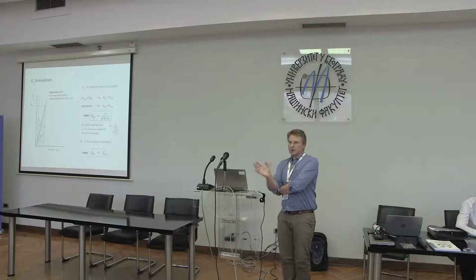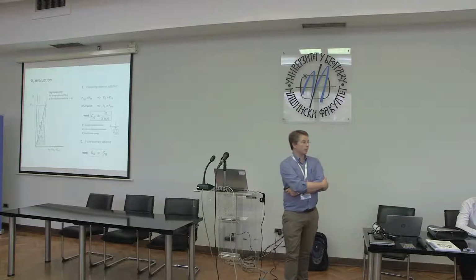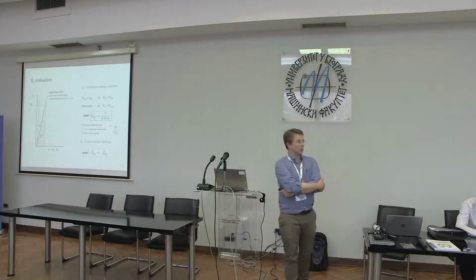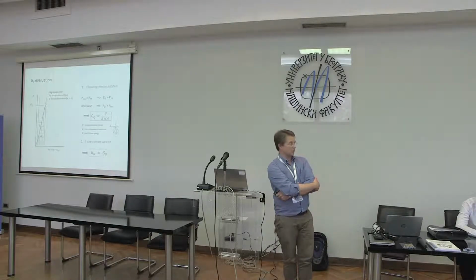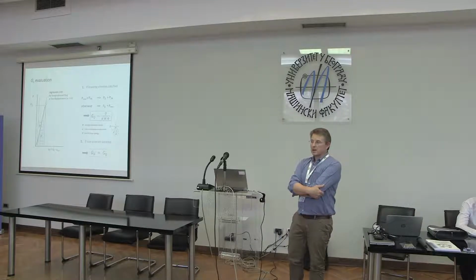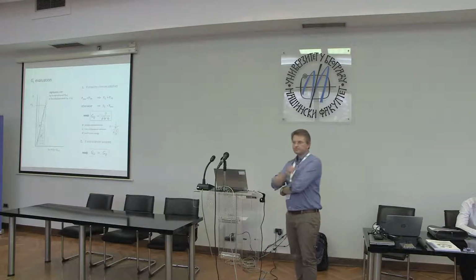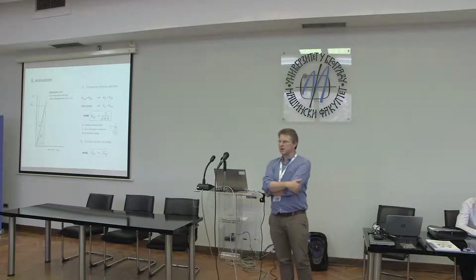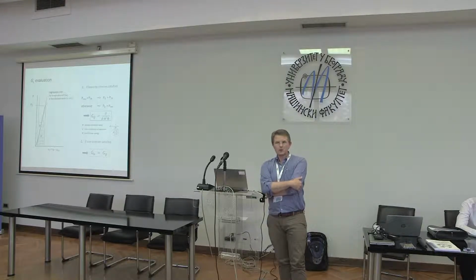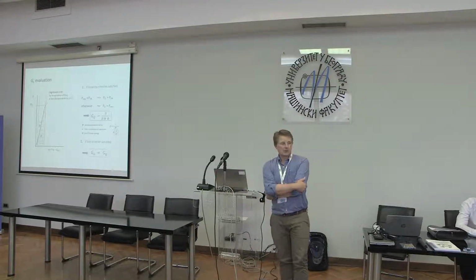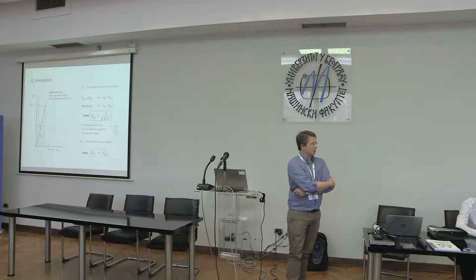Just as an aside, the main problem we've had with adopting what we describe as a multi-specimen approach to measuring J1C in polymers is controlling the level of crack growth required. Of course, you have to put a notch in. The initial conditions of the notch may not be so critical because you're assuming that there will be plasticity. But what is absolutely critical is that you can control a certain amount of crack growth.